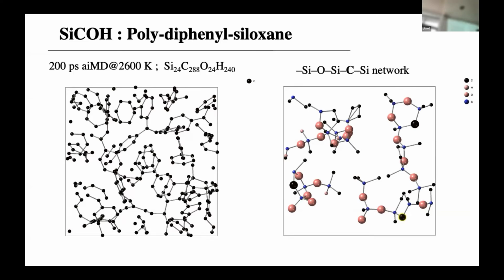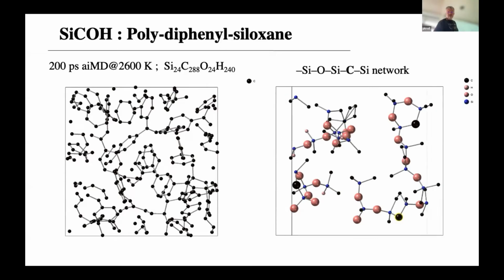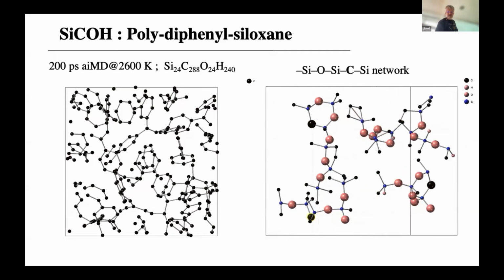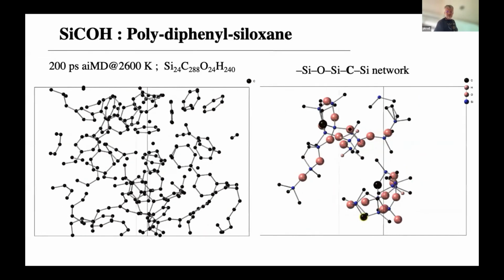Here is one carbon that is between two blue silicons. There is one in there, and we find, if I'm not mistaken, here's a second. Yes, the big fat carbons are always between the silicons. So these carbons do insert there. There are mechanisms that the phenyl groups are disrupted and provided carbon to the siloxane group. So in the end, this is the polymer backbone. Things happened. Come on, everybody wiggles here.